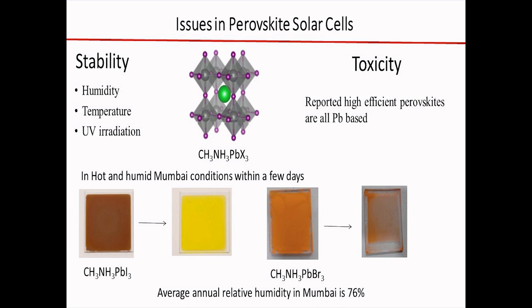So this is how the film of methylammonium lead iodide looks like when we freshly prepare it, and this is a methylammonium lead bromide film, how it looks when freshly prepared. But when we keep it in hot and humid Mumbai conditions, within a few days this film turns to like this, and this film will turn to something like this.